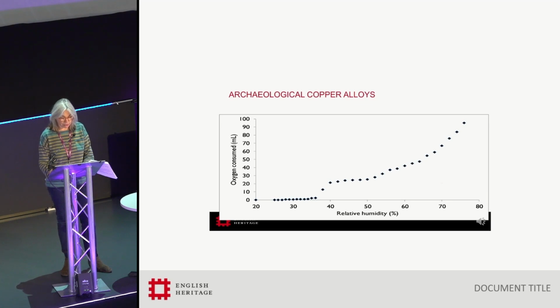As this graph shows, on the vertical axis we have oxygen consumed, on the horizontal we have increasing RH. And as you can see, it's at 35% RH that we start seeing the big uptick in oxygen consumption and therefore corrosion.